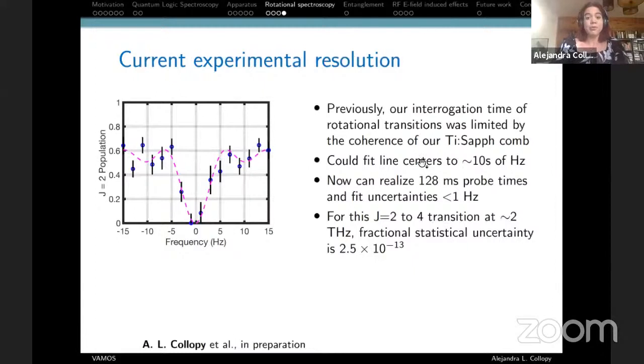So we've been able to improve our experimental resolution. Before, we could fit our line centers to some tens of hertz. And now we're able to realize 128 millisecond probe times. And that gives us fit uncertainties of less than a hertz. So over here, I'm showing a frequency scan as we're driving a transition from J equals 2 to J equals 4. And we're able to significantly narrow down this frequency scale. And for this particular transition at 2 terahertz, this is a fractional statistical uncertainty of 2.5 times 10 to the minus 13.